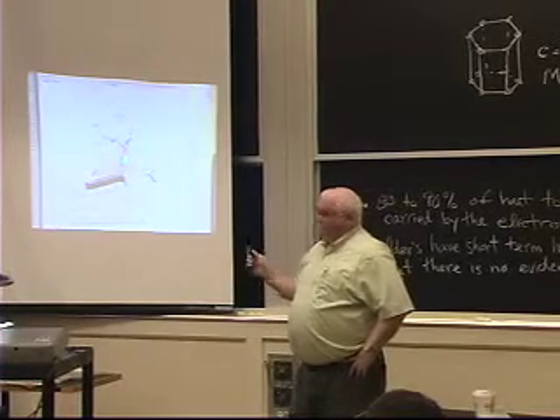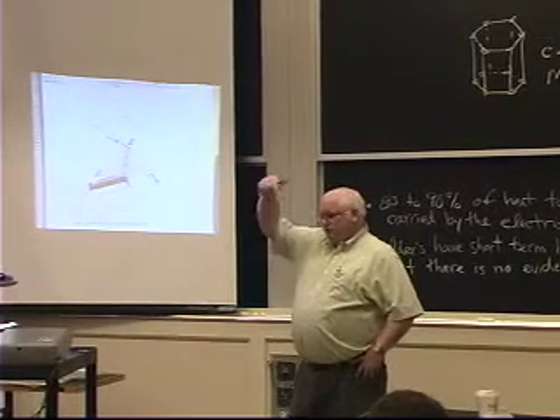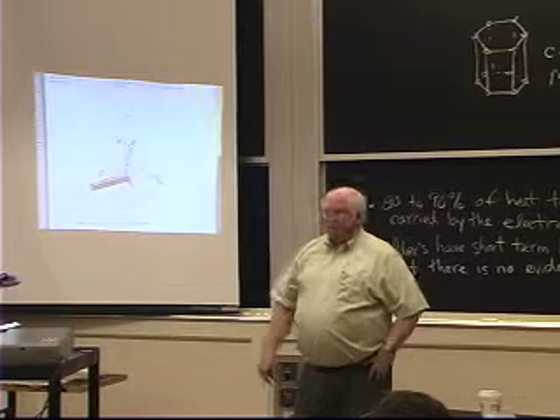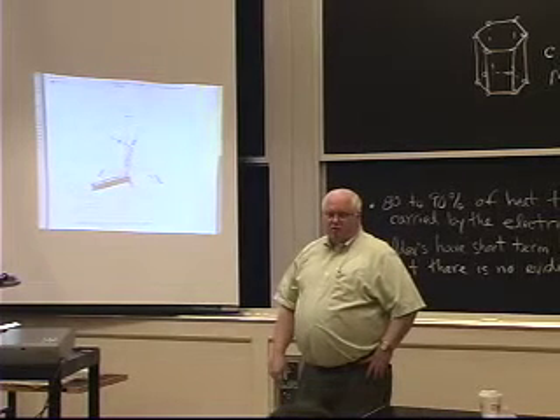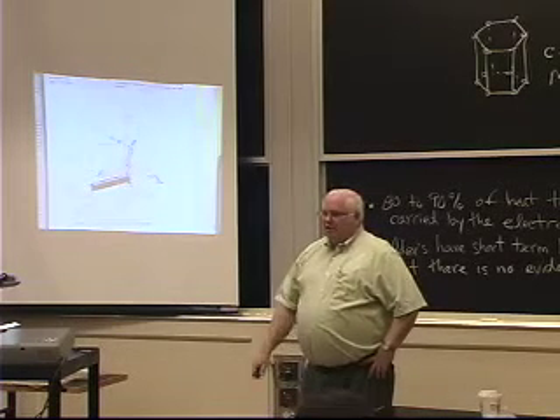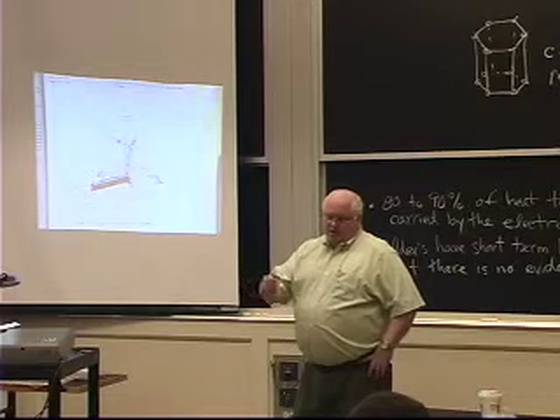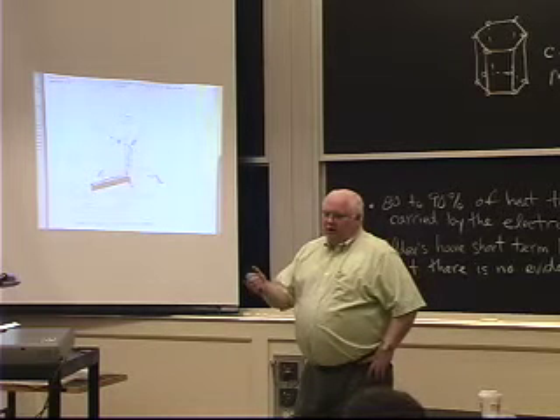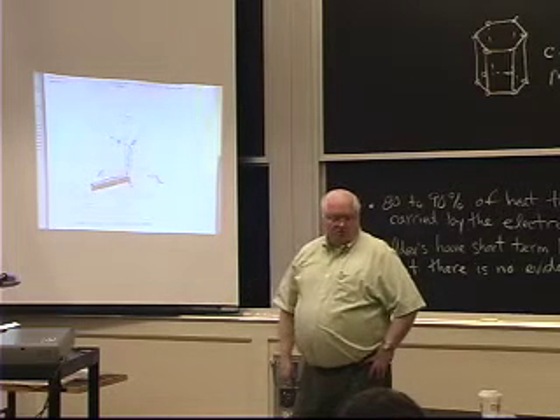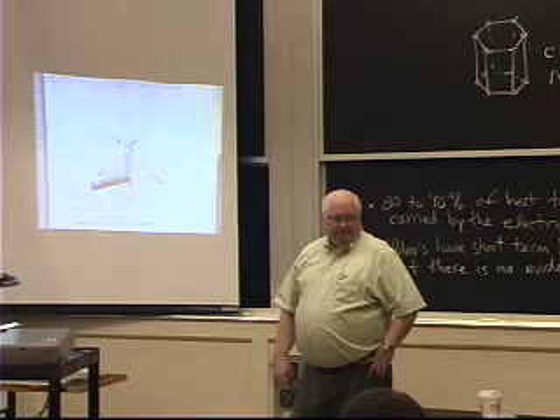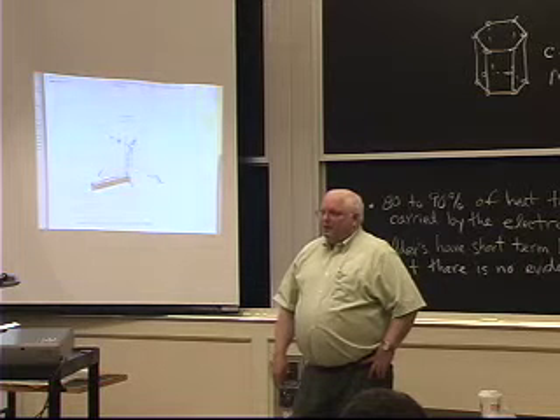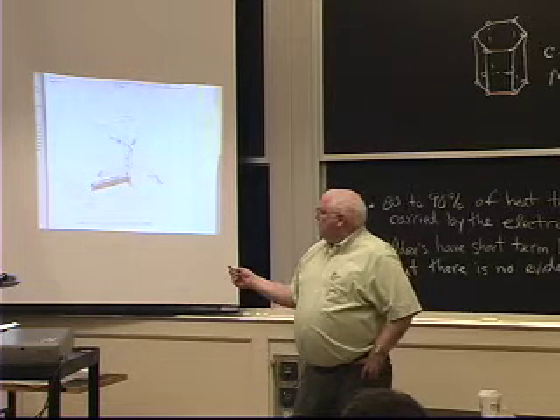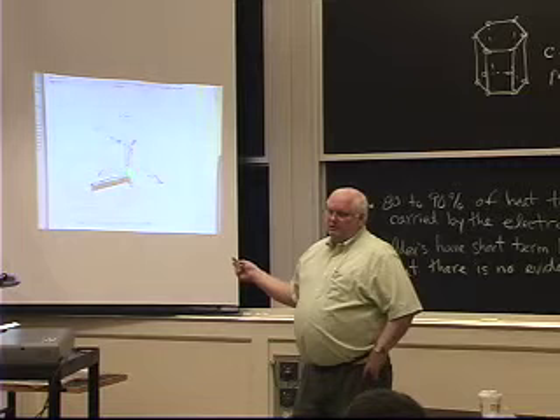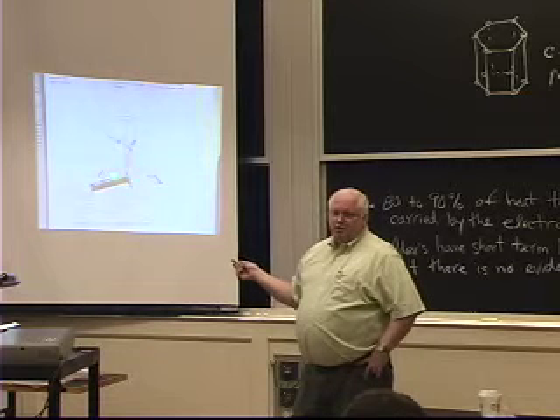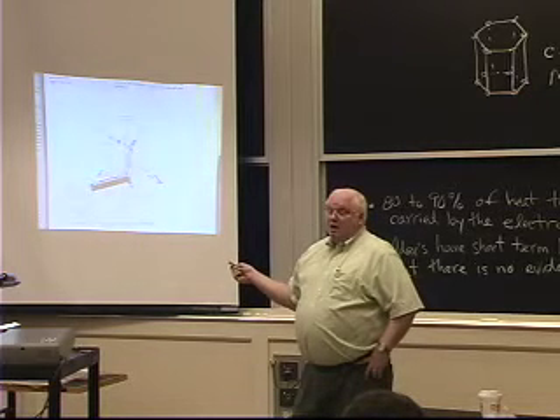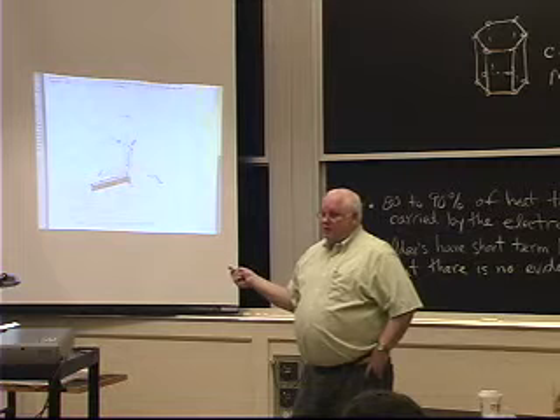You're feeding that wire down through there fairly rapidly. I mean, you can see the wire feeding in kind of like that speed. You're melting very quickly. You can lay down 60 pounds an hour with this process, whereas a guy welding by hand might lay down 3 or 4 pounds an hour. And does that affect the strength of the material? If you're welding really high strength steels, this probably puts in too much heat, lowers it, and softens the steel, which is another reason. Although they do it for HY80, they do it for HY100.